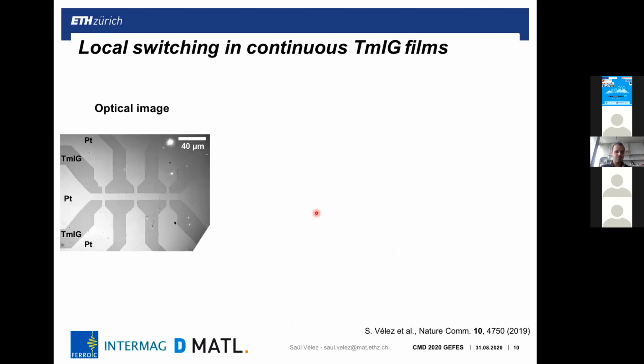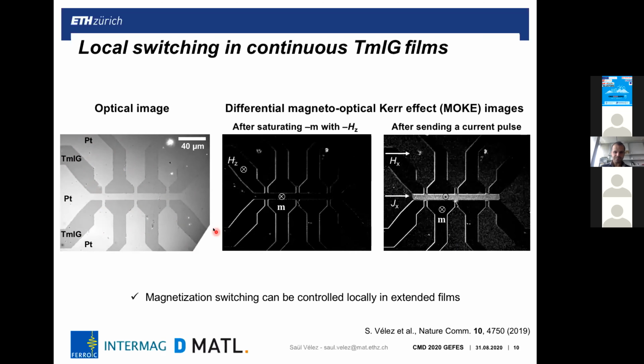But the question is how this switching occurs, because when we send a current pulse, we see a magnetization switch in the Hall bar region only, because that's the part that you can read out in electrical measurements. But now we want to see how this switching occurs in the system, because we have to think also that we only etch the platinum and the thulium iron garnet is continuous. So this is a differential Kerr image that is sensitive to the out-of-plane magnetization. So that's in the differential mode.